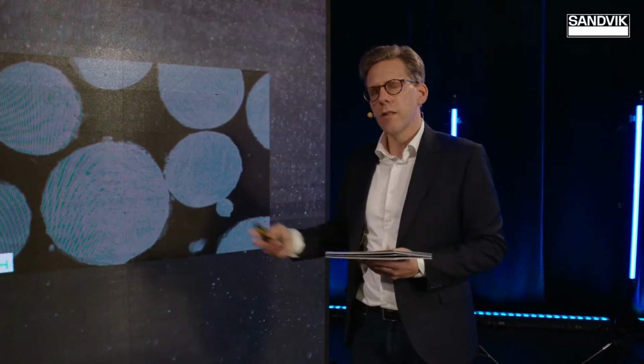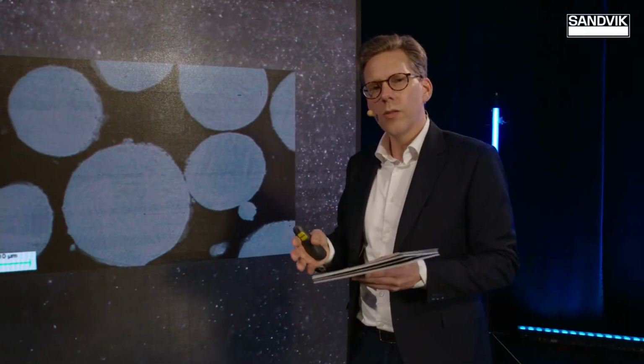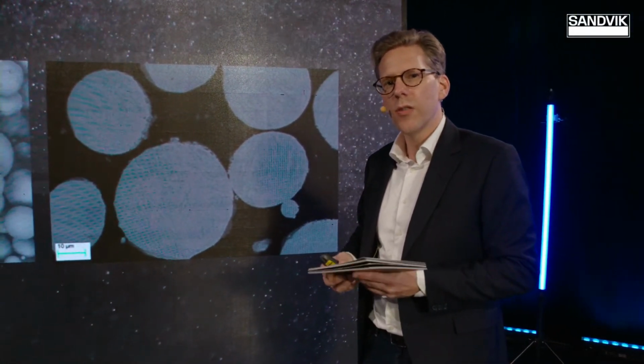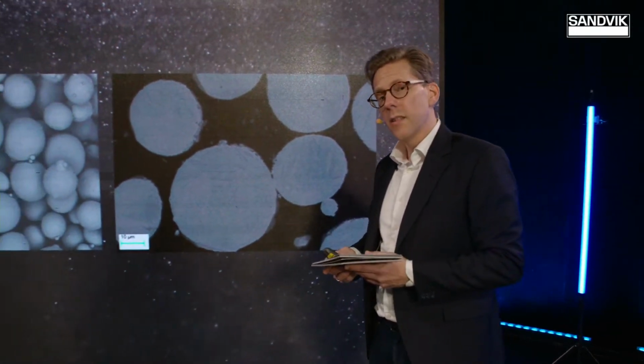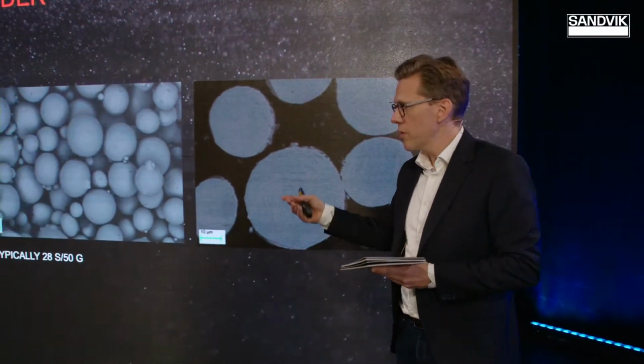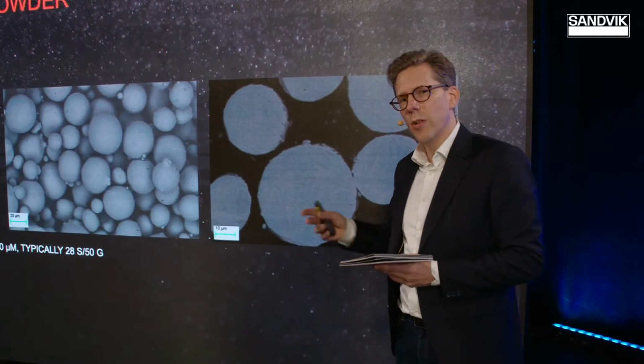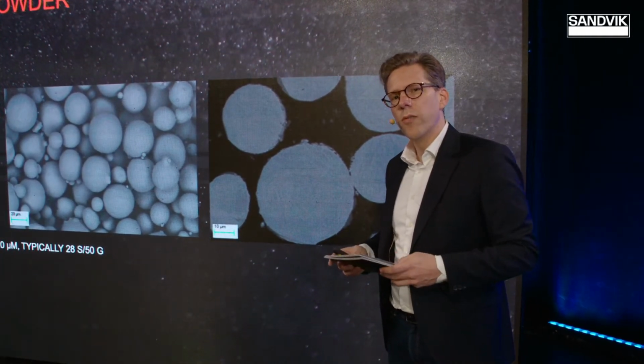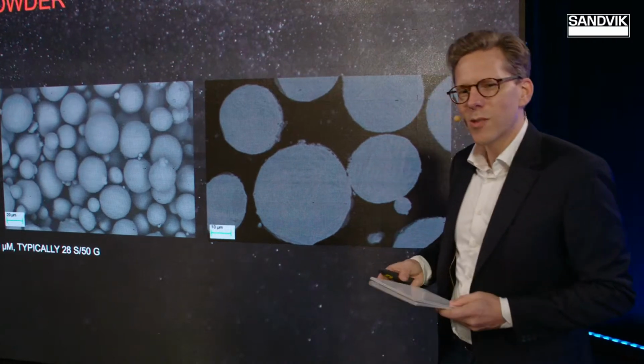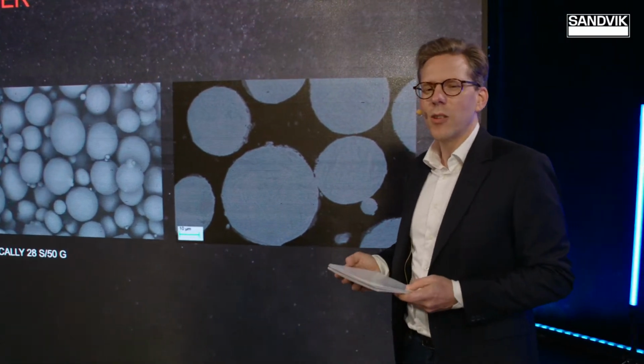And a typical measure that I mentioned is flowability. Typically we pour the powder into a small funnel and measure the time it goes through. And for this powder, it takes slightly below 30 seconds, more precisely 28 seconds for 50 grams to pass this small funnel. So we are very proud of this product that is relatively new for us.